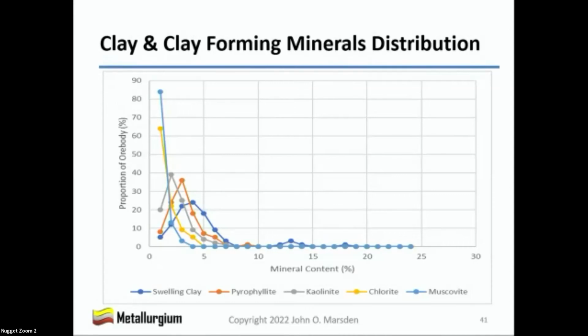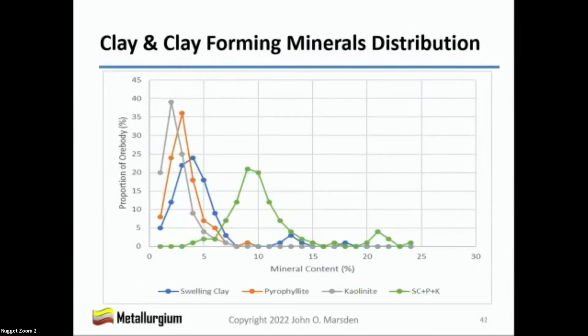He realized that the swelling clay content was bimodal, with about 6% of the blast hole samples containing more than 10% of the swelling clay content. And these samples also contained elevated pyrophyllite, kaolinite. He realized that a small percentage of the samples contained the highly elevated swelling clay, pyrophyllite, and kaolinite. So he plotted these up on their own in the next graph.